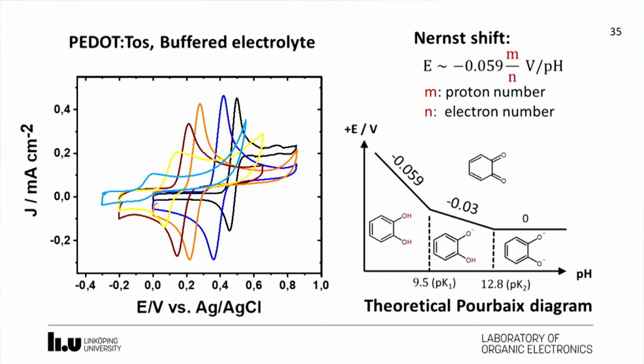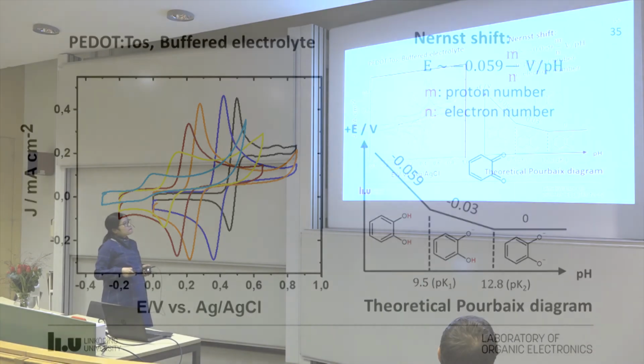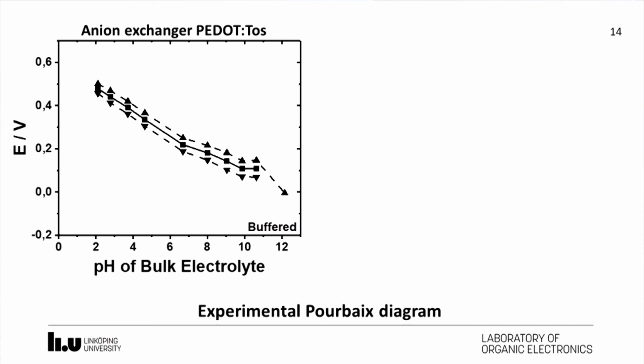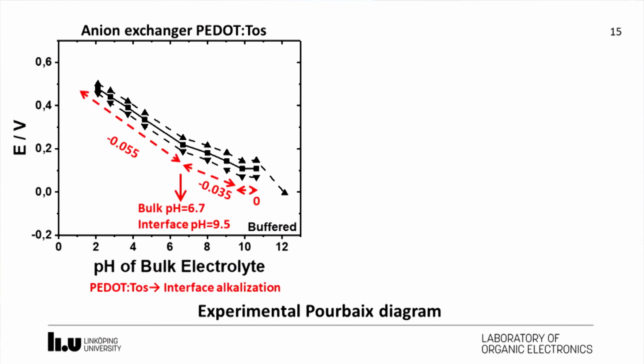For catechol reactions, the theoretical Pourbaix diagram consists of 3 slopes for the equilibrium. In the acidic region, the slope is close to 0.059 volts per pH, followed by 0.03 volts, and then a 0 slope for a fully deprotonated catechol reaction to quinone. This is the result we found on PEDOT:TOS. And you can see, indeed, there are 3 slopes corresponding to the theoretical plot, but we also found that the transition points shifted to low pH values. For example, the first transition point happens at a bulk pH around 6.7, which should happen at the first pKa value around 9.5. So it means that when the bulk pH was still 6.7, the interfacial pH had already reached 9.5.